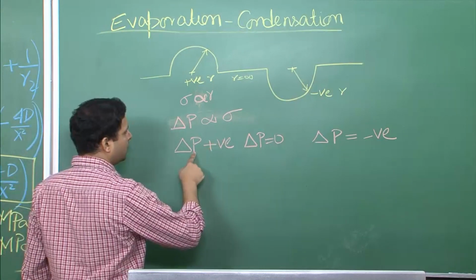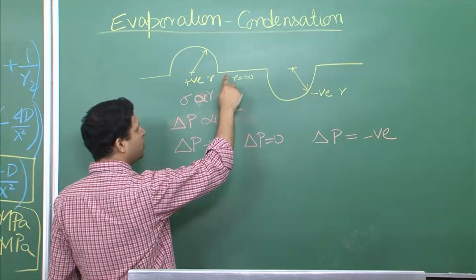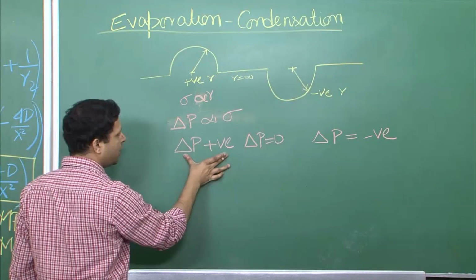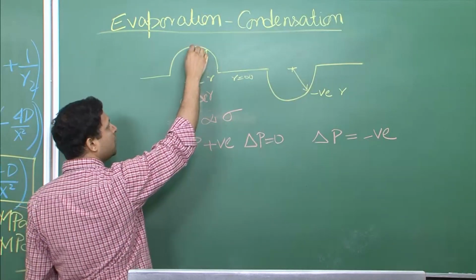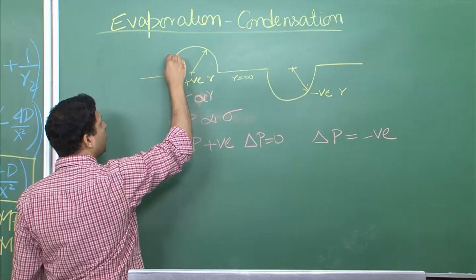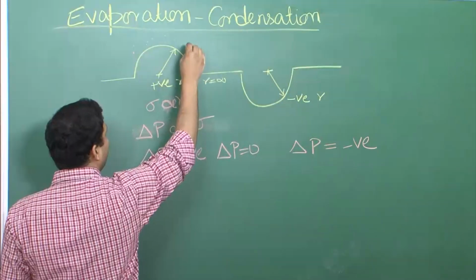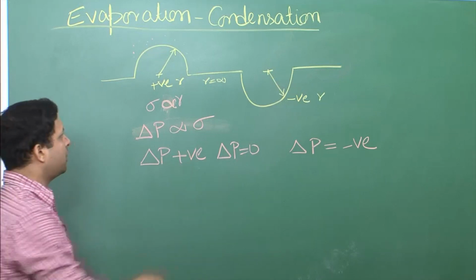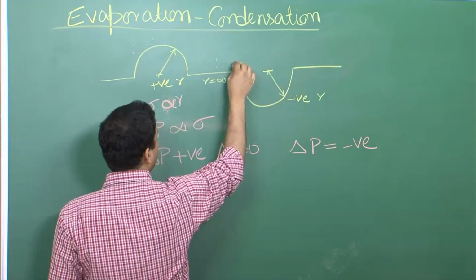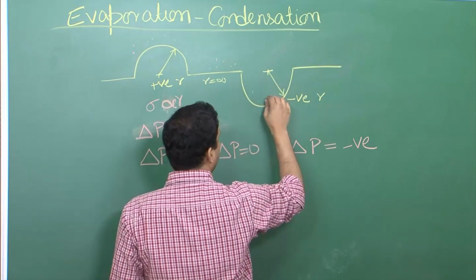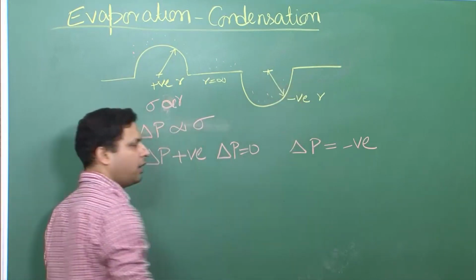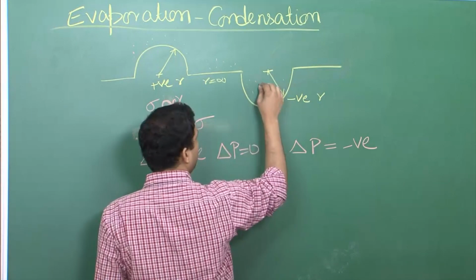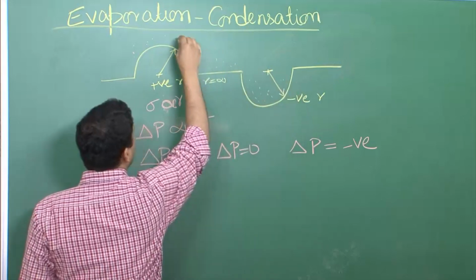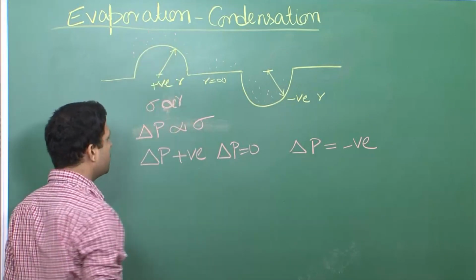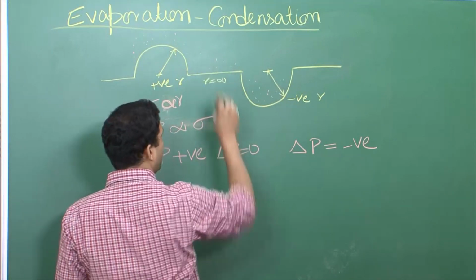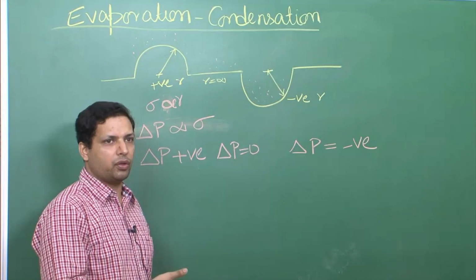We are looking at delta p with respect to a flat region. So, basically when we say delta p is positive, what we mean is that the partial pressure, if you look at the particles over here, they will have a higher partial pressure with respect to what you have in this flat region, and even higher compared to this negative radius of curvature. So, there is a much higher partial pressure over here.